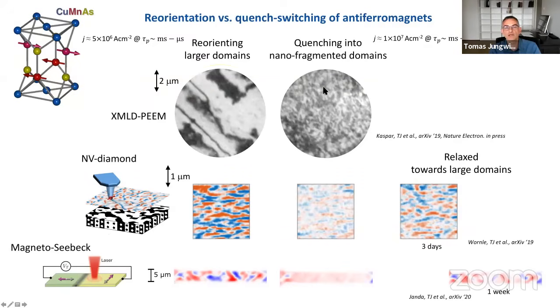We saw it not only in this synchrotron X-ray magnetic linear dichroism studies, but also in the magneto-optical laser imaging in the lab, which I already introduced earlier in the talk, and also by another study, which is the nitrogen vacancy diamond magnetometry. Also in these experiments, we see that starting with large domains and applying these slightly larger pulses than the ones that we normally use for the reorientation switching, we shatter the large domains into these small nano-fragmented states. Now in these laboratory experiments, we can then wait days or even weeks, and we can then re-image